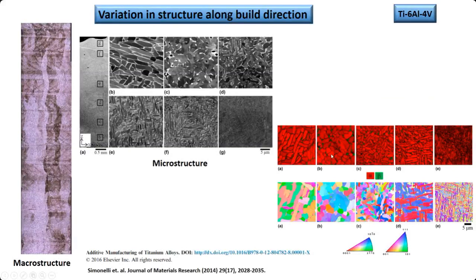This is the electron backscattered diffraction image where we see this microstructural change very clearly. So we have this columnar lath structure in case of alpha and beta. We have the comparatively gray phase which is alpha, and the white phase here is beta, shown here as red and black, or greenish. We can see that this can be columnar or more or less equiaxed, and the size is decreasing, giving us a completely refined structure.